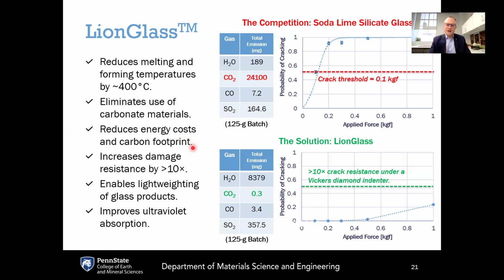Another exciting feature of LionGlass is the improvement of damage resistance. The upper right plot shows the probability of soda lime silicate glass cracking under a Vickers diamond indenter. The indentation cracking threshold is defined to be the force at which the probability of cracking is 50%. For soda lime silicate, that's about 0.1 kilograms force. LionGlass pushes that up to more than a factor of 10 greater. We maxed out what we could do with our indentation equipment here, going to 1 kilograms force and still only had a 25% probability of cracking. So it is a dramatic improvement of damage resistance.